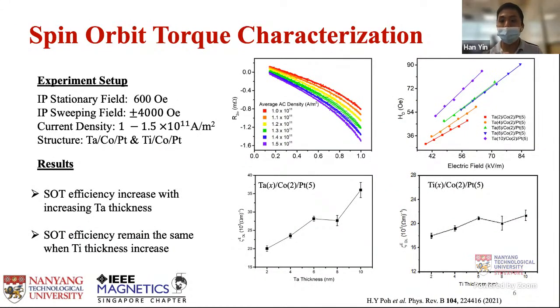So the spin orbit torque has been characterized in our experiment, where we have used a structure of Ta/Co/Pt and Ti/Co/Pt. We have varied the thickness of Ta and Ti to observe the change in SOT efficiency. For the result, we can observe that the SOT efficiency increased with Ta thickness. I can see this on this graph over here.